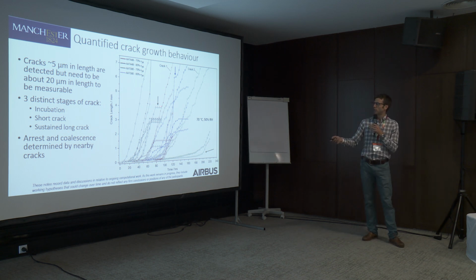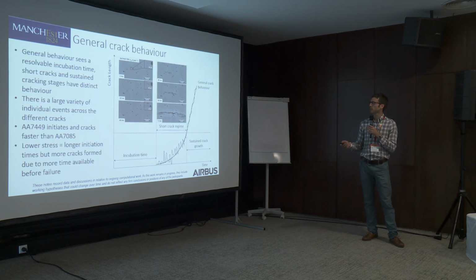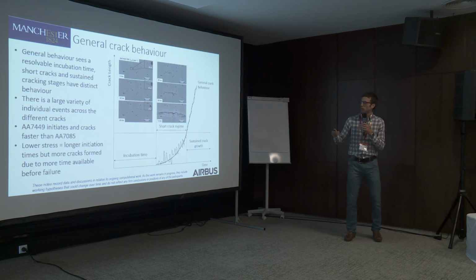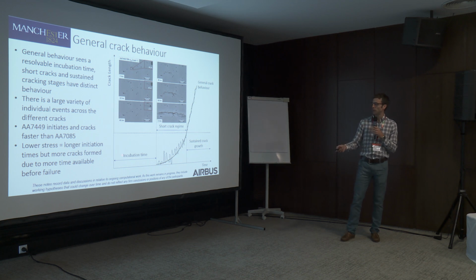Like one event here, you can see these cracks have arrested, but that's because these 2 cracks here have coalesced and basically shielded the growth of the cracks here. But we can also see other jumps, and so there's quite a lot of interaction between these cracks as they grow on the sample.